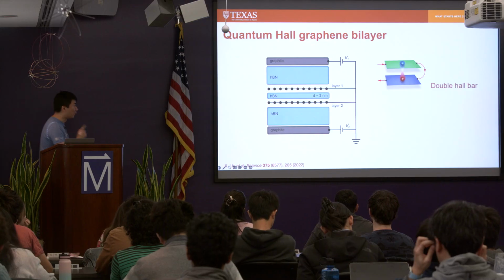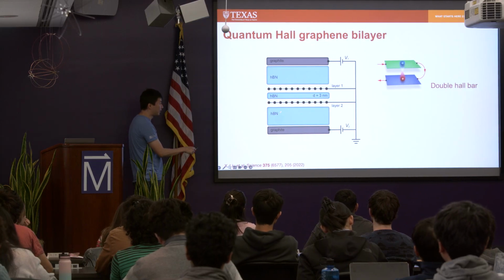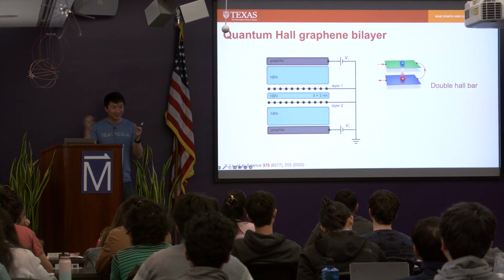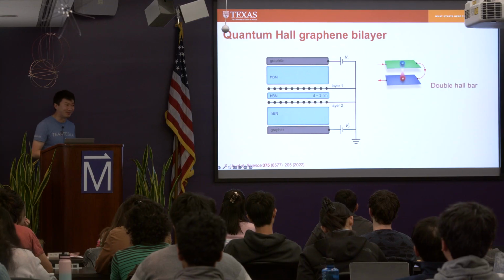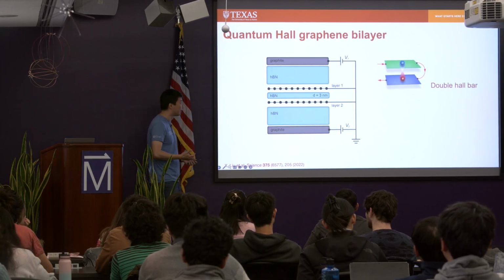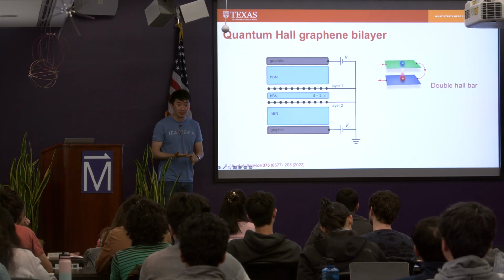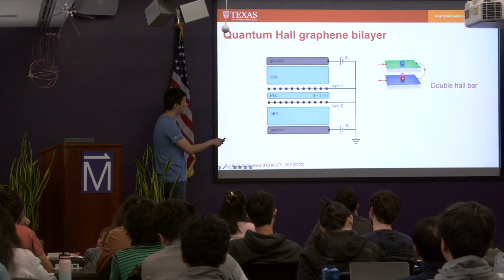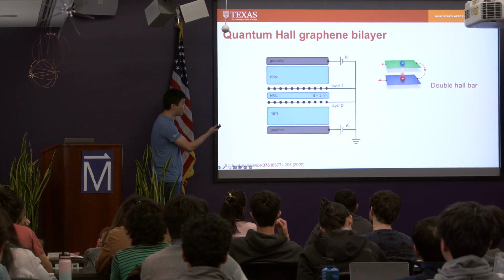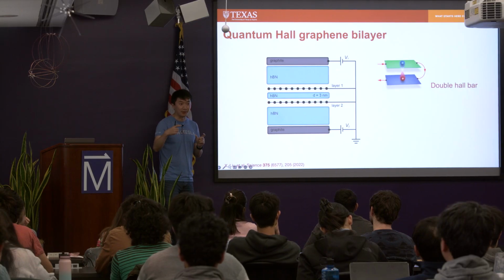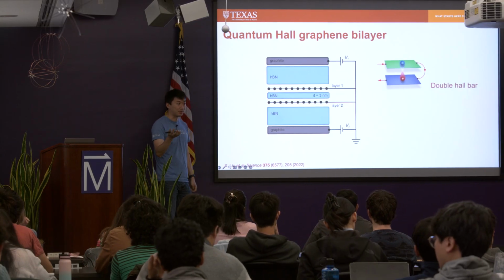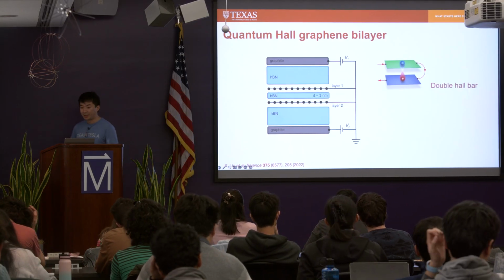Right. When you have this structure, you still need to make a decision on what kind of device to make before you do transport measurement. Usually there are 2 options, right? We can pattern each layer into a square shape, and we call this double Hall bar, right? Each layer functions as a Hall bar. You flow current, you can measure longitudinal and transverse resistance.